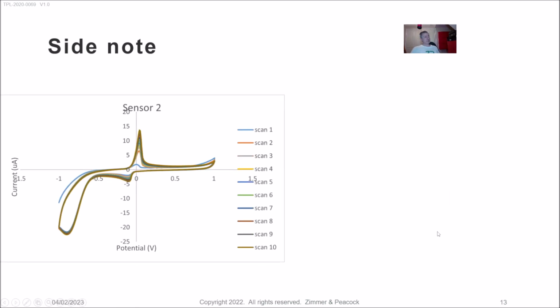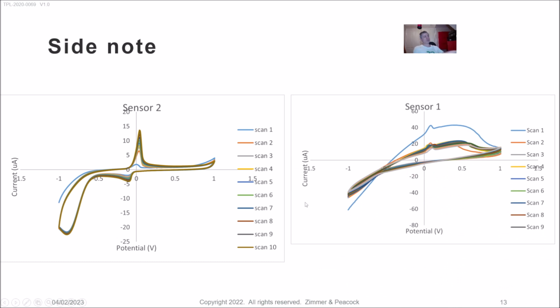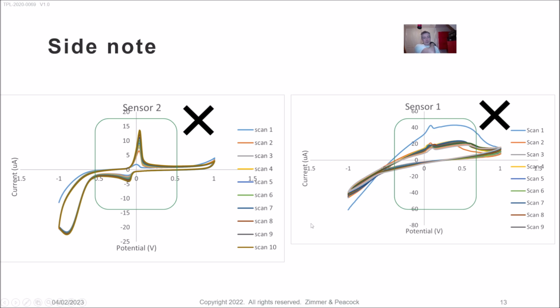Also, the use of CV. If we see something gross, like these two CVs that I would say are showing gross defects. This CV, one of the CVs on the left, is showing what we call a contamination of silver, and the one on the right, I don't know what it's doing, but it does not look good. At which point Julie can come in there and just reject these straight out and say, there's something went wrong, which is good, because then you won't carry these electrodes forward in your manufacturing process, because obviously the later you catch these problems, the more you've invested in them, and then basically the more money